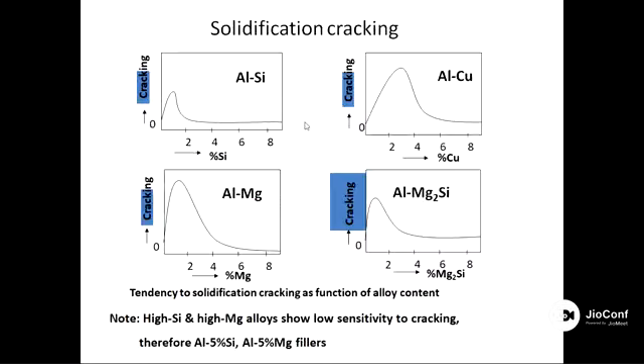So in a nutshell, these are the various diagrams giving an idea about cracking versus various alloying elements like percentage silicon, cracking versus percentage copper, cracking tendency as a function of percentage magnesium, and cracking tendency as a function of magnesium silicides. So you could see if your consumable in your welding filler metal uses silicon up to 4 percent, the cracking tendency increases when there is less silicon present, up to 2. But when the silicon is present more than 2, the peak slopes back and it becomes continuous, so you have less cracking susceptibility.